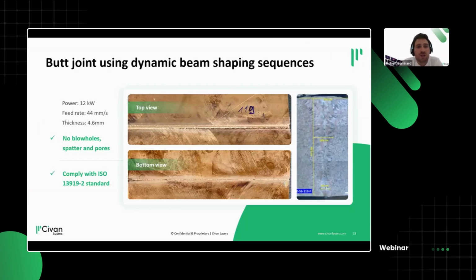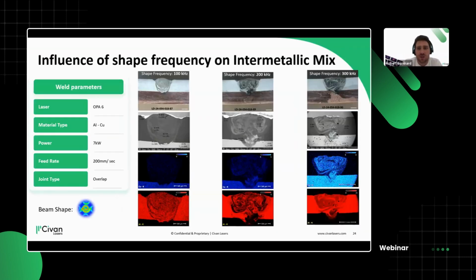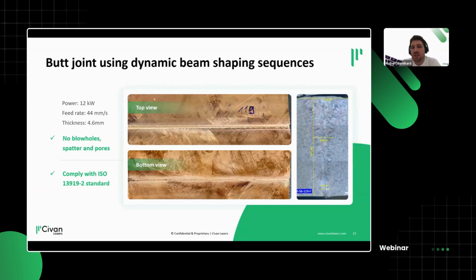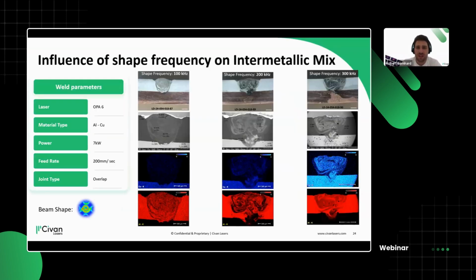Well, and this finally leads to things like busbar welding, laser welding of around 5 millimeters material thickness without blowholes and spatters. So I think this is also a very interesting application where with our laser you can do copper welding and even advance and enhance on typical static ring-core approaches, and you don't even need to bother with blue and green then.